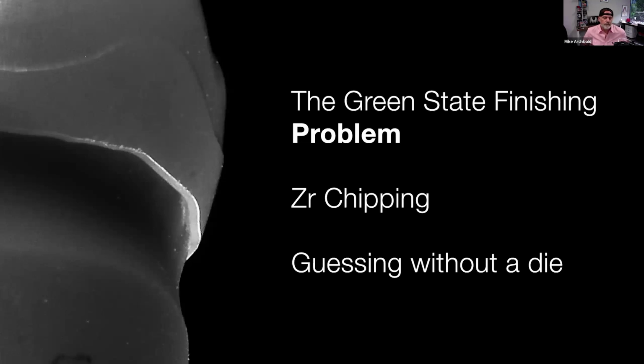And of course, the green state is softer and you can be able to work with it easier. But then there's a couple problems. The first problem is, a lot of green state zirconias, especially if they're isostatically pressed and they have larger particle sizes, that zirconia is kind of sensitive. It can start to chip or flake away. And so you really got to be careful with it. It's in more of a fragile state.